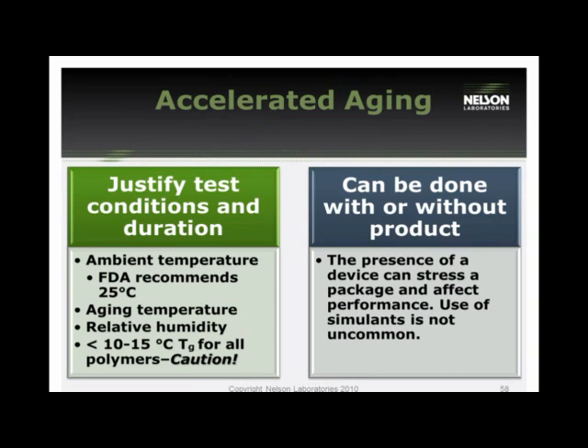Okay, when you're doing accelerated aging, you're going to have to justify the test conditions and the duration, especially if you move outside of what the FDA is used to seeing and usually recommends. The nominal or ambient temperature that they like to see is 25 degrees with an accelerated aging temperature of 55 degrees. Moving away from those, they're definitely going to be looking for different justifications on why you feel that those are appropriate and reflective of the environment that you use. Additionally, you're going to want to take a look at your glass transition point, which is TG. If you have any polymers, you're going to want to make sure that you stay between 10 and 15 degrees below that value, because as you put them into the temperature, they start to melt and can have effects on the interaction between the package and the device itself.